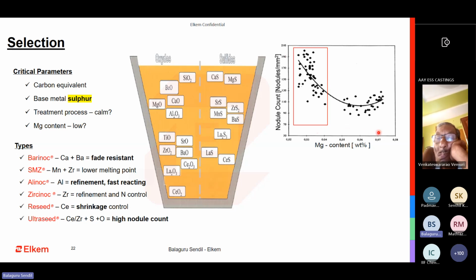If I keep increasing the magnesium, my nodule count will come down. When my nodule count comes down, it opens a can of worms. It can cause shrinkage, it can cause carbides, it can cause slag and dross to get accumulated. So it's a very, very bad situation. Nodule count is very directly correlated to graphite expansion. More nodule count, more graphite is expanding, so more heat is given out. When more heat is given out, the metal naturally gets expanded while it is shrinking towards the end. So this is the fundamental.